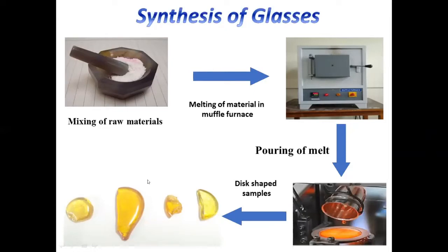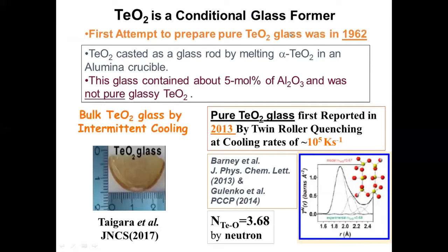So glass can be made out of oxide materials like silica, B2O3, tellurium dioxide, P2O5, germania. Germania is germanium dioxide. Those glasses are transparent. And here we show the pictures of some tellurite glasses, and they are also transparent. So tellurium dioxide is a conditional glass former, and it forms glasses with difficulty when it is present in the pure form. And we need very high quenching rates. Quenching means rapid cooling of the melt. We need quenching rates of the order of 10 raised to power 5 Kelvin per second to get pure TeO2